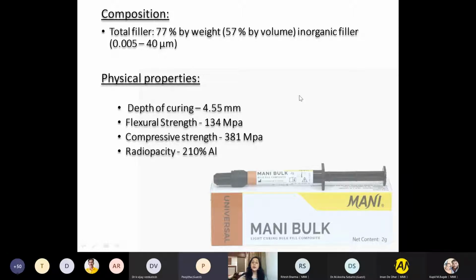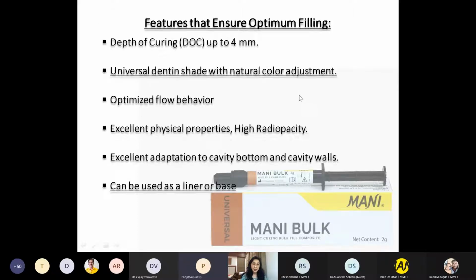So your technique and your time is fast, and you are able to complete your restorations in a limited amount of time. The total filler content is 77% by weight, which is great. Compressive strength is very good, and the radio opacity is also very good, 210% again. The depth of cure is 4 millimeters.